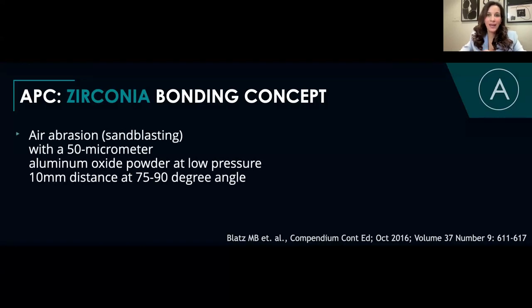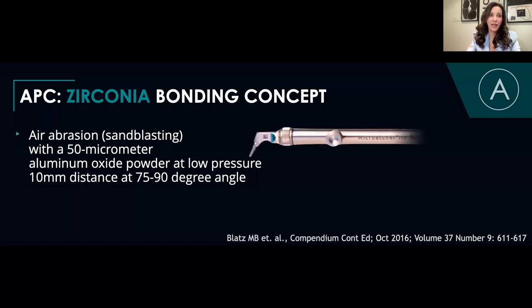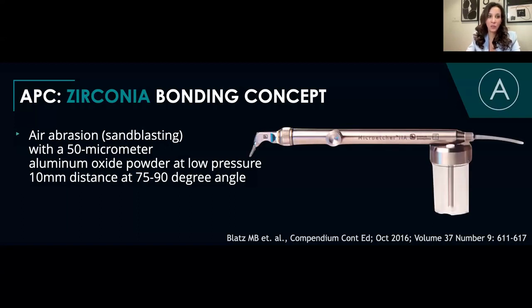So unlike a glass ceramic that can be etched with hydrofluoric acid, remember that zirconia, I said at the very beginning, consists of densely sintered zirconium dioxide crystals. So there is no glassy matrix. That's why it can't be etched. Glass can be etched, zirconia cannot be etched. So in order to roughen the surface of zirconia, which will increase the bonding strength, you need to air abrade it. And the recommendation is to air abrade or sandblast with 50 micrometer aluminum oxide powder at a low pressure. So that takes care of the A, so for air abrasion.